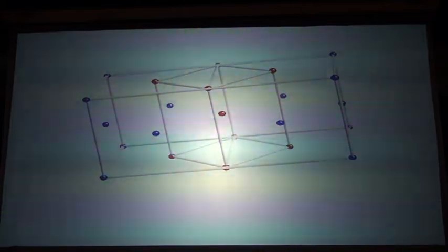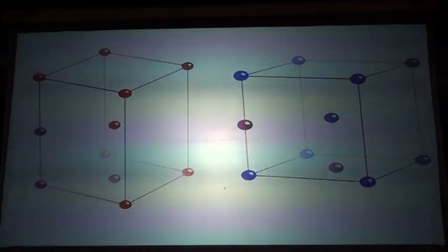Now, carbon atoms which are present in the austenite: there's only one octahedral interstice per iron atom in austenite. But there are three octahedral interstices per iron atom in ferrite. So all the carbon atoms that are present in the austenite will end up in just one set of octahedral interstices in the ferrite. So if we have a displacement transformation, carbon will always end up along one set of cube edges, making the lattice tetragonal. Whether or not it wants to be tetragonal, it is forced to be tetragonal. Okay? So basically, when we do the Bain strain, the carbon atoms will all end up along the z-axis of that cell. So when a displacement transformation happens, you will necessarily get a tetragonal lattice when carbon is present.